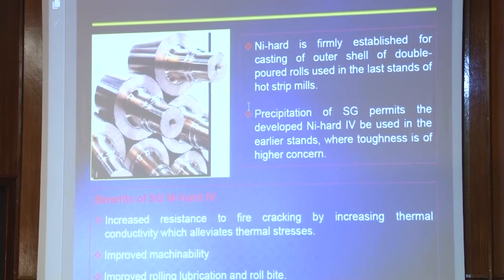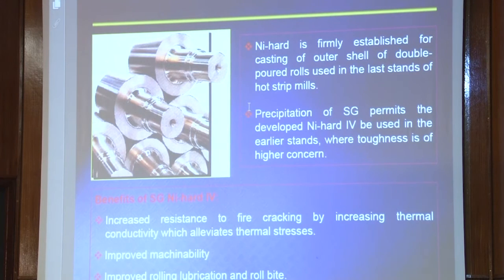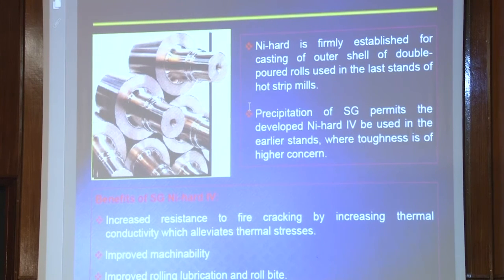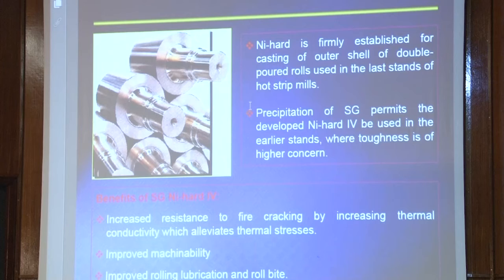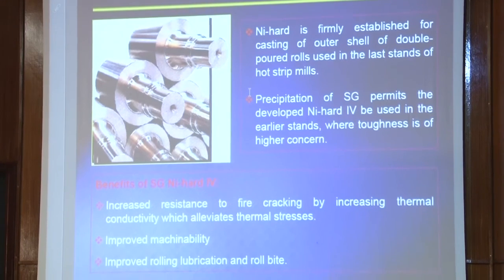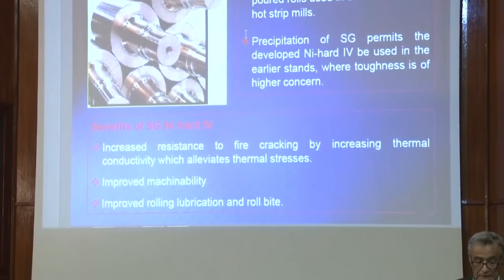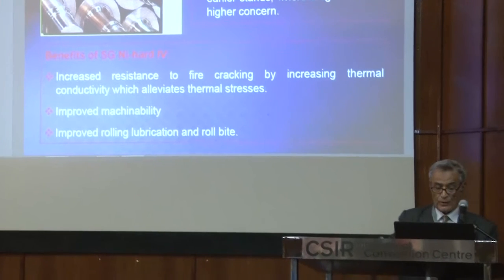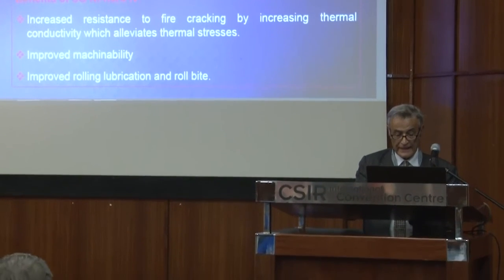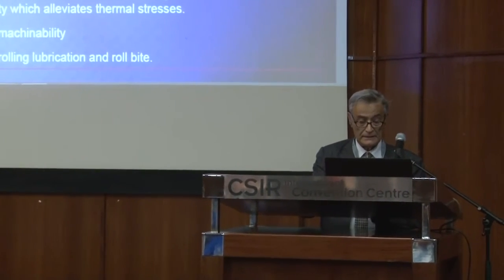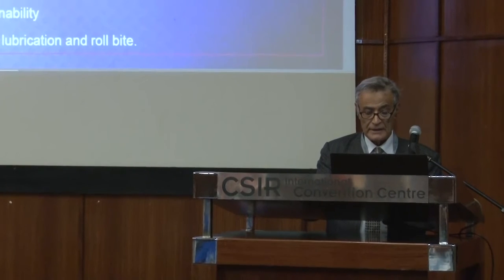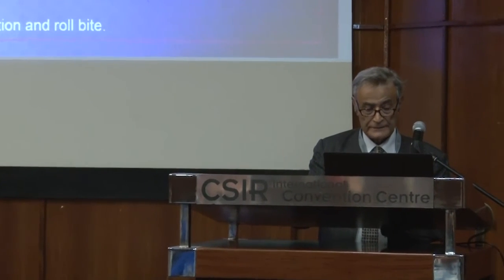Now the hard nickel alloy, as we call it, is firmly established for casting of the outer shell of double poured rolls used in the last stands of hot strip mills, and the precipitation of spheroidal graphite permits the development of hard grades to be used in the early stands where toughness is of higher concern. The benefits of spheroidal graphite are increased resistance to fire cracking, improved machinability, and improved rolling lubrication and roll bite.